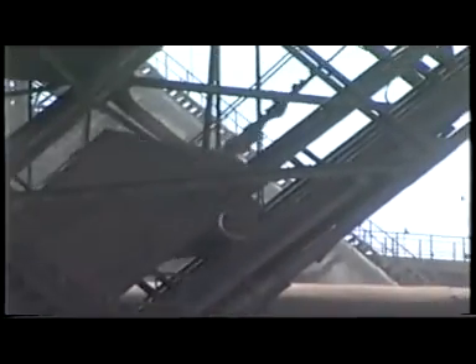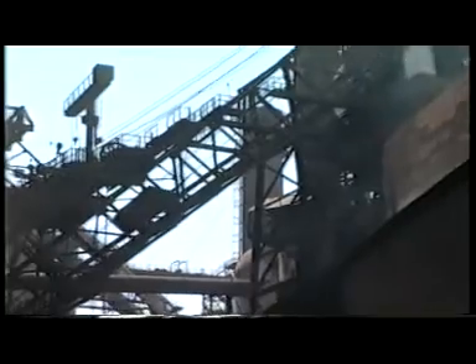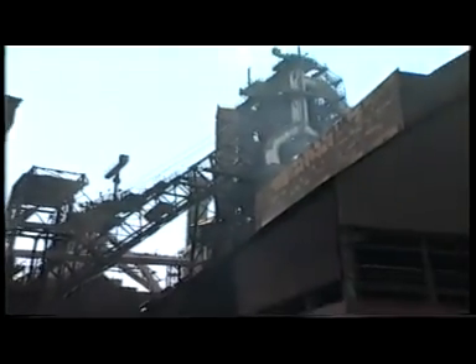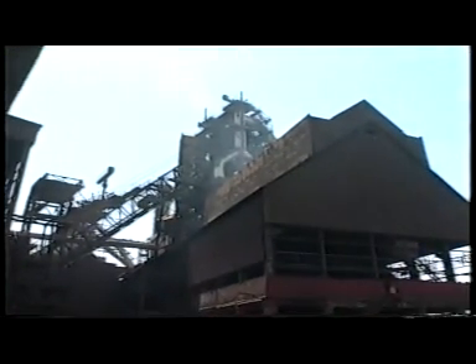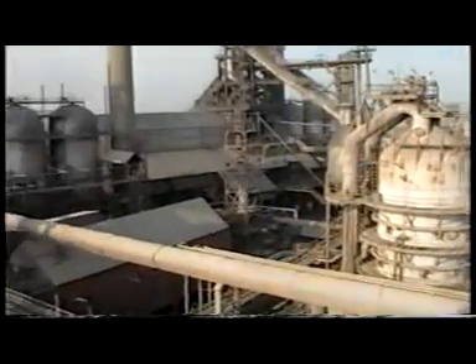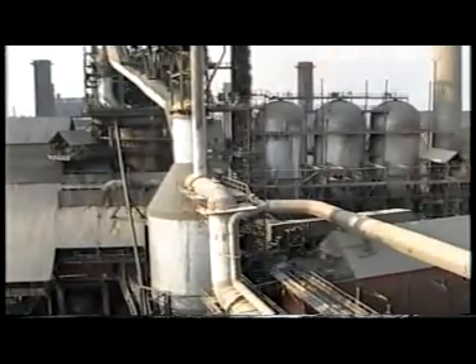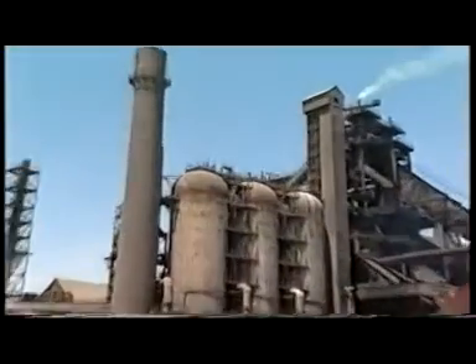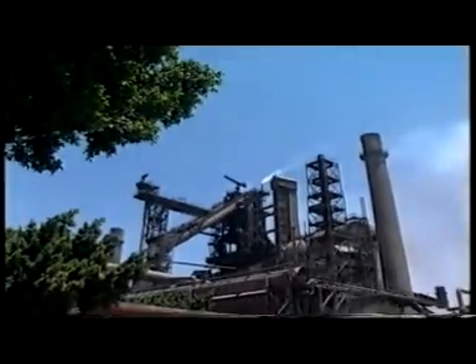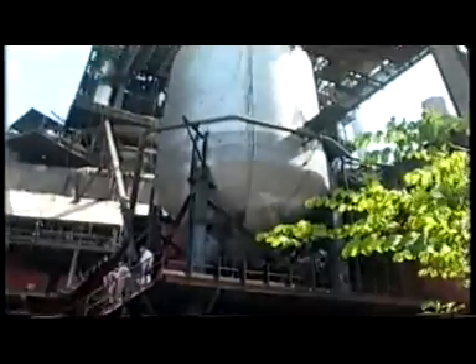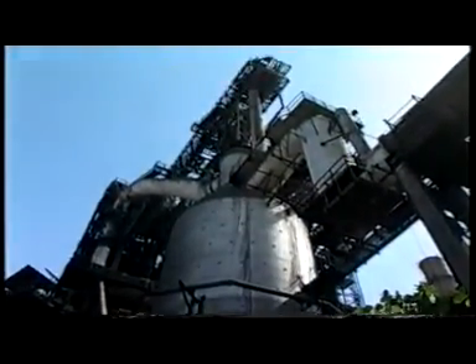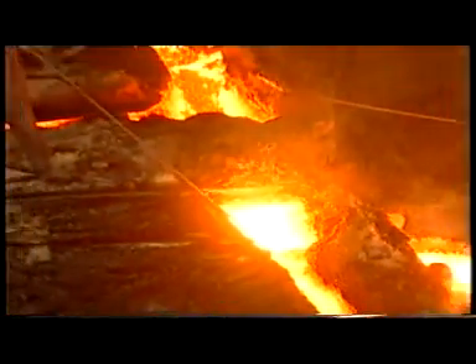The sinter is charged inside the blast furnaces by means of ascending and descending skid cars. Some materials are added to the blast furnace charge, such as limestone, fluorspar, and dolomite by certain amounts. The lower charge inside the furnace meets a rising up current of gases evolving from the reactions between coke and hot air blast enriched by oxygen and natural gas.